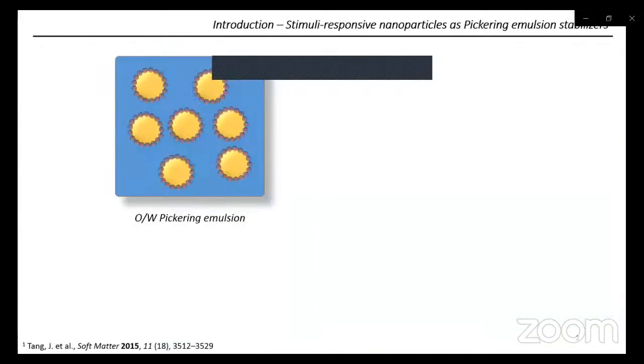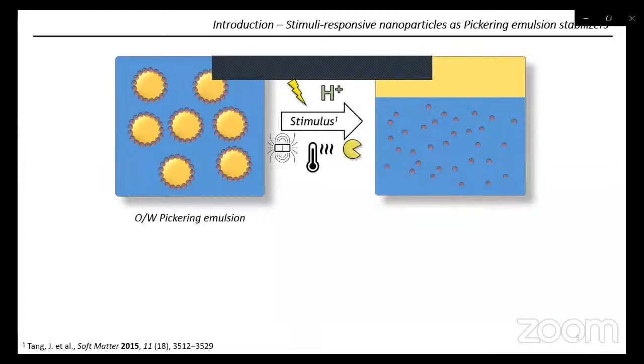There is another topic of interest, which is stimuli responsive nanoparticles. Here you can stabilize an oil-water Pickering emulsion, and when applying a stimulus, which can be a pH, magnetic field or temperature, you induce the desorption of these nanoparticles from the interface. As the droplets are no longer stabilized, they merge together, we say they coalesce, and it ends up with the full macroscopic destabilization of your emulsion.